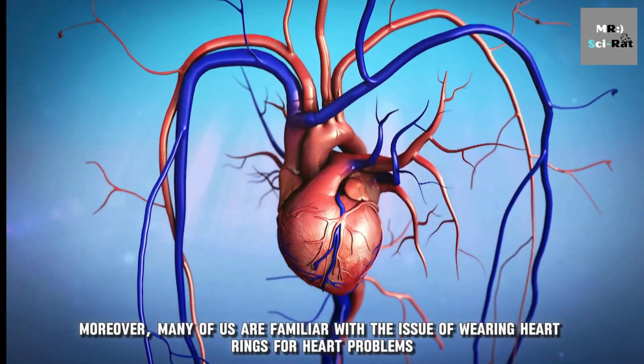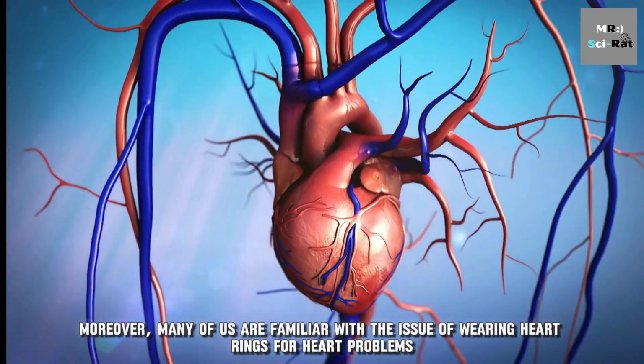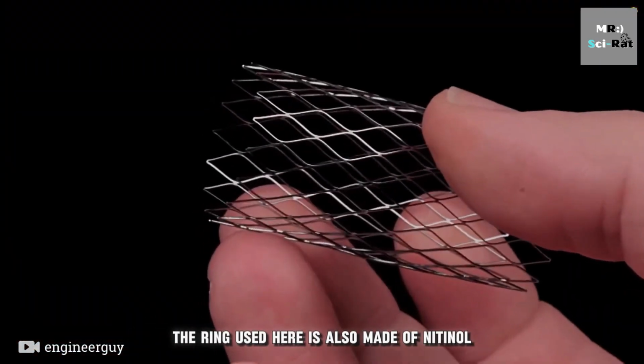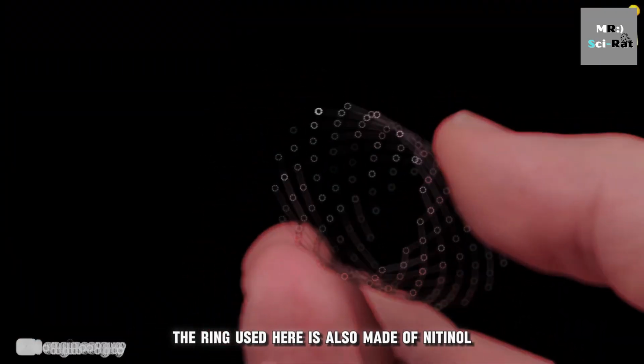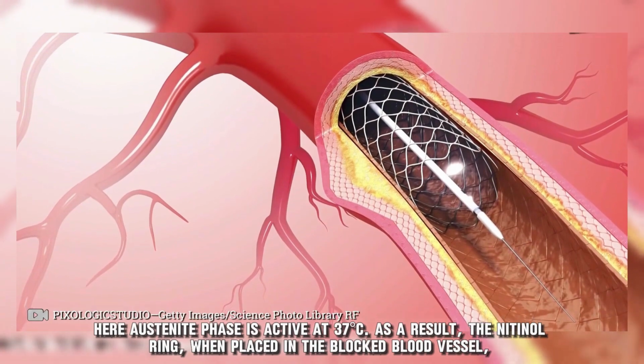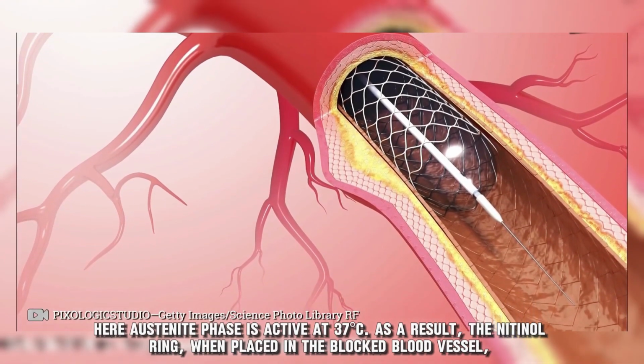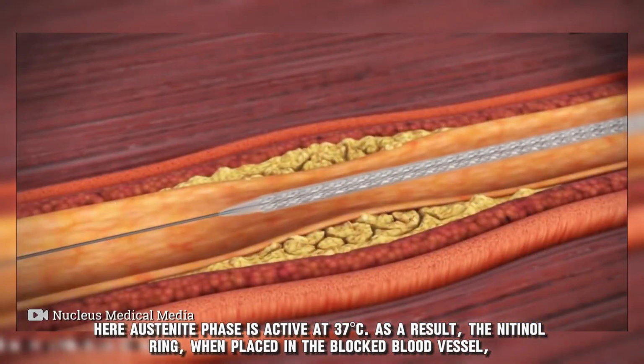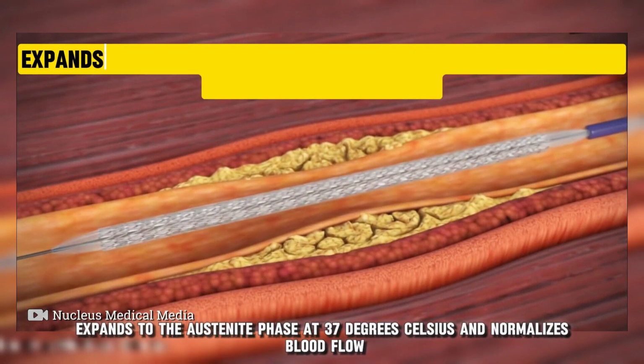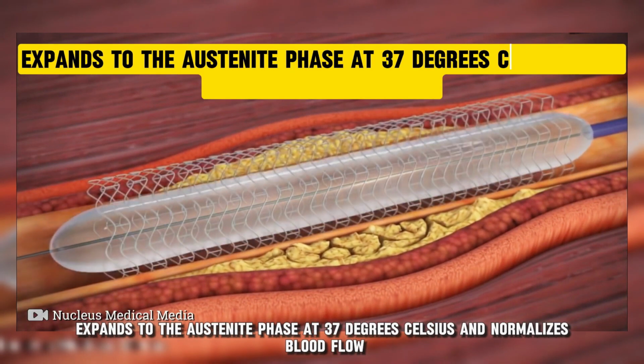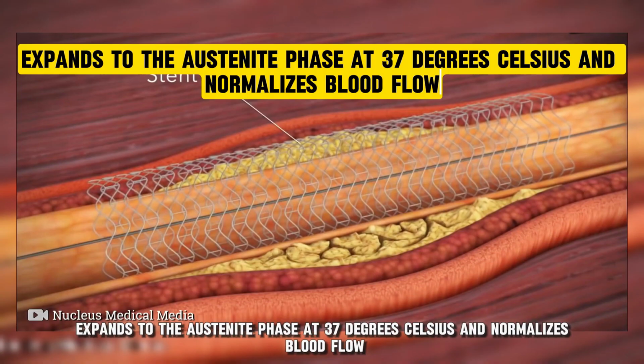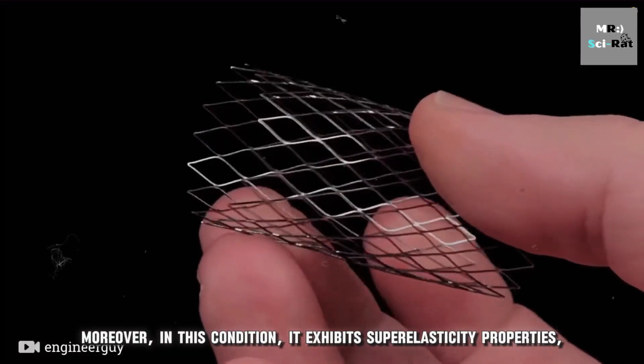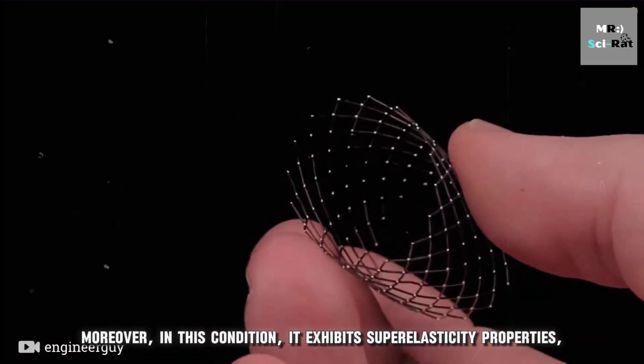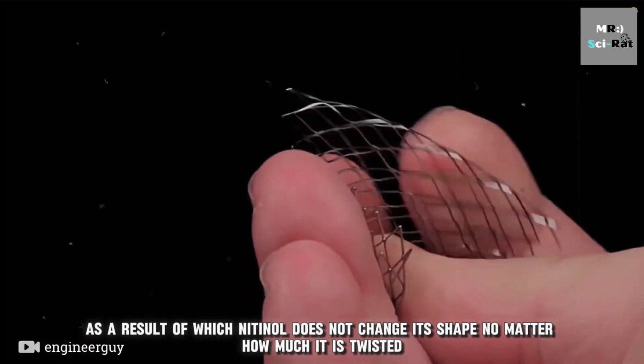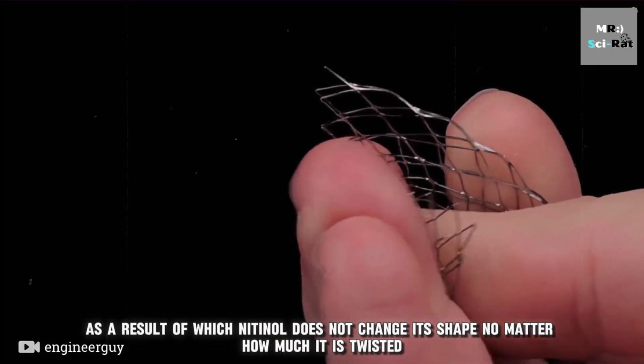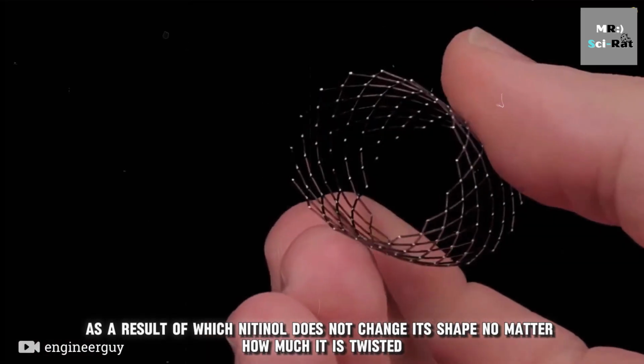Moreover, many of us are familiar with the issue of wearing heart rings for heart problems. The ring used here is also made of nitinol. Here, austenite phase is active at 37 degrees Celsius. As a result, the nitinol ring, when placed in the blocked blood vessel, expands to the austenite phase at 37 degrees Celsius and normalizes blood flow. Moreover, in this condition, it exhibits superelasticity properties, as a result of which nitinol does not change its shape no matter how much it is twisted.